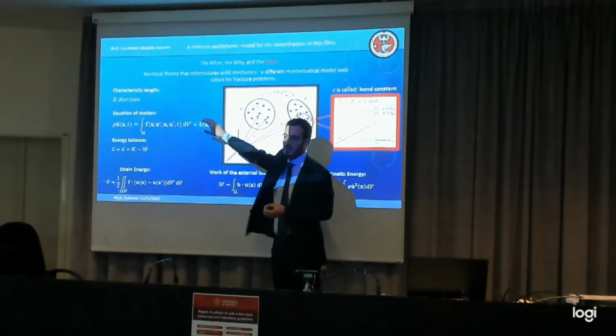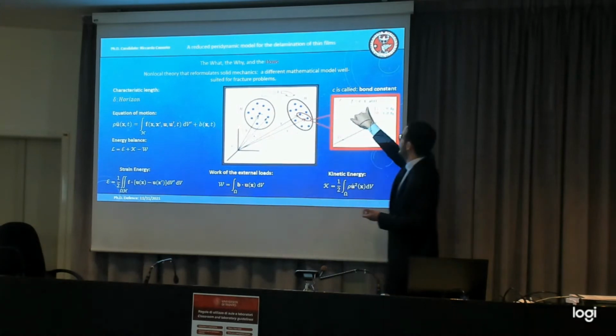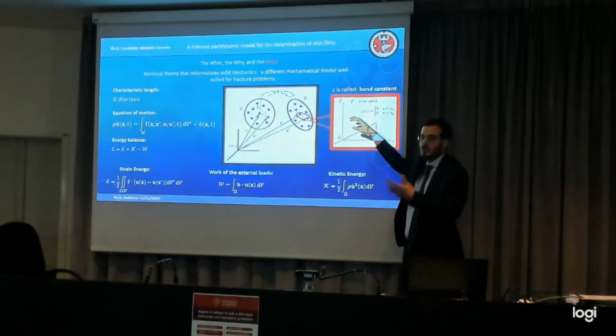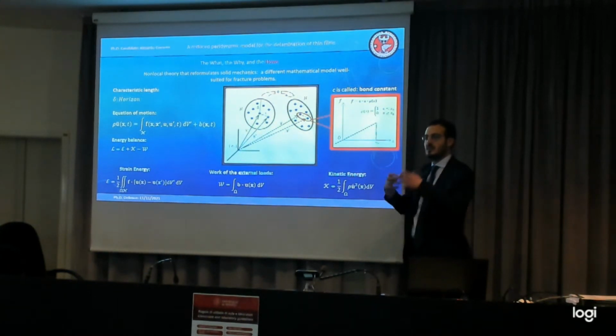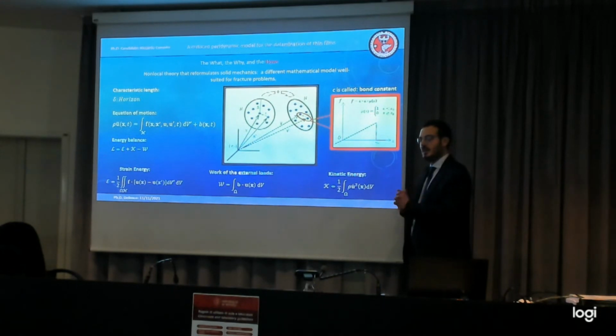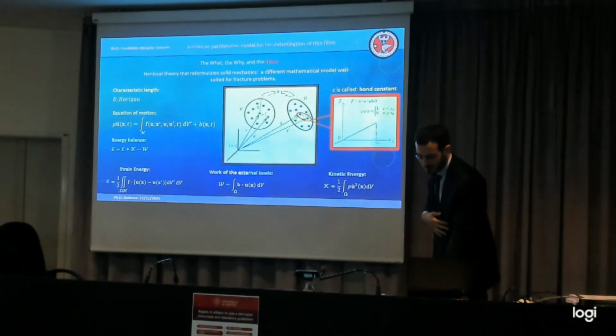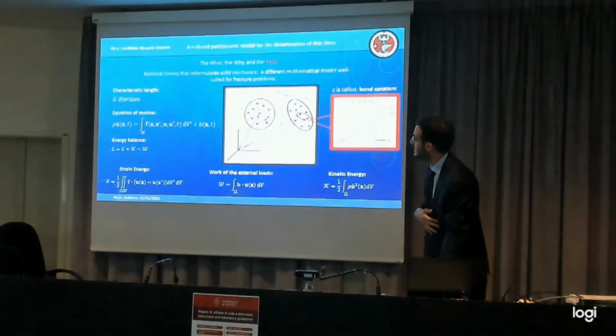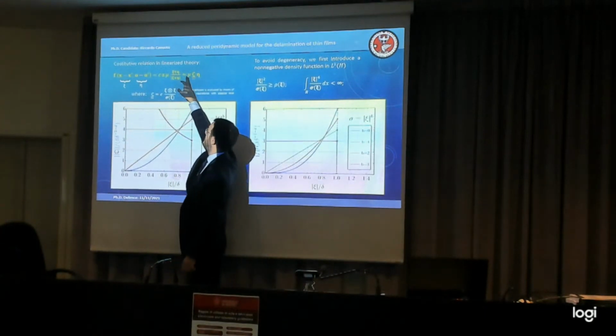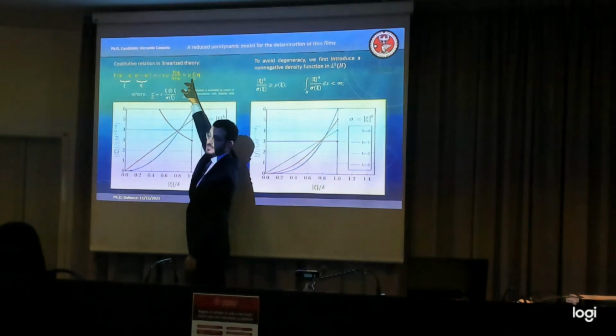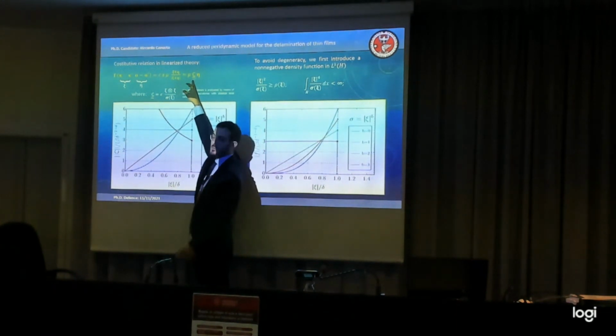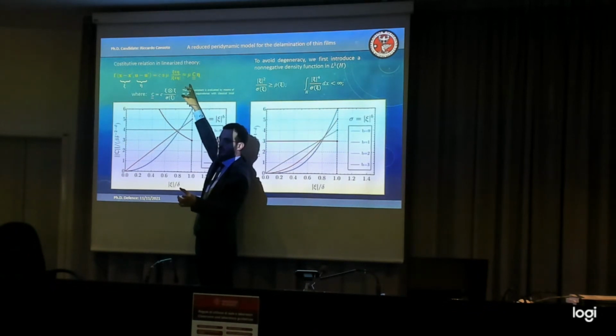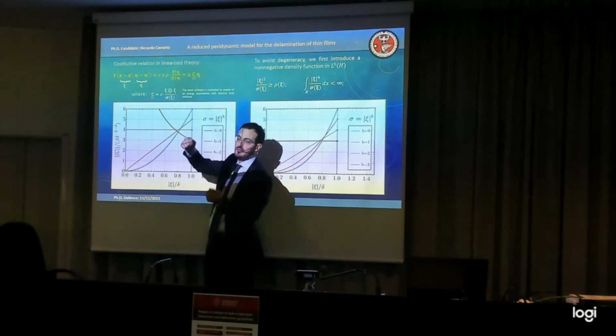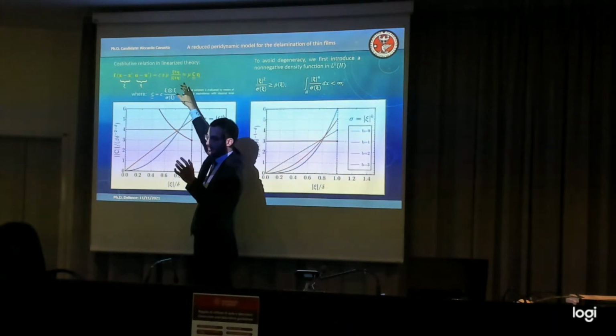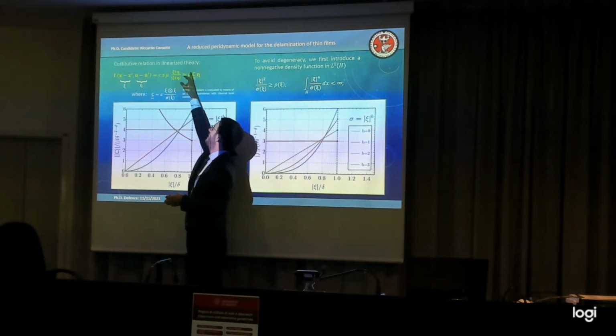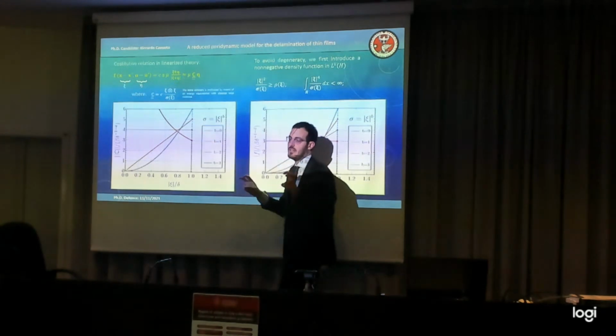You take this, you place it in the equation of motion, and this function over here is an unknown of the problem. So you need to understand if under a certain level of deformation, some bonds are breaking irreversibly. So it's implemented inside the constitutive relation, and it appears. This is the vectorial linearization. This is the relative displacement between 2 points. This is a second-order tensor describing the relative position. It only depends on the displacement and on the relative position. If you don't linearize it, it also depends on the final configuration. This is only depending on the reference configuration. And so this is capturing all the irreversibility and non-linearity in this term.